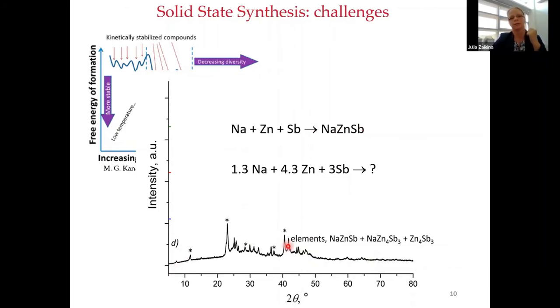So the diffraction peaks here are marked with stars. There will be also binary compounds and some of the low intensity diffraction peaks, which suggest that there might be another compound present. However, if we have several phases present in the sample, establishing the structure of one of the compounds becomes a particularly difficult task. So we really need to find a good synthesis method which allows us to target specific composition. So if we narrow down the systems we are looking at toward the systems containing alkali metals,